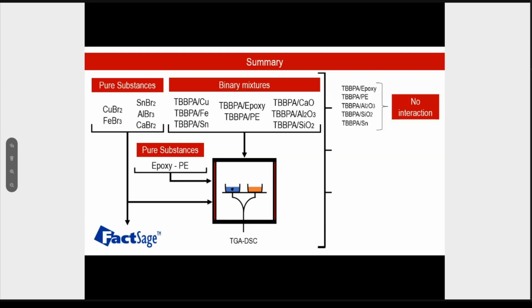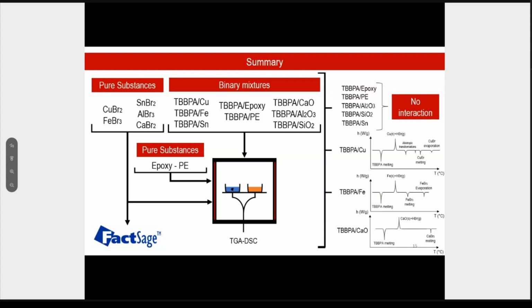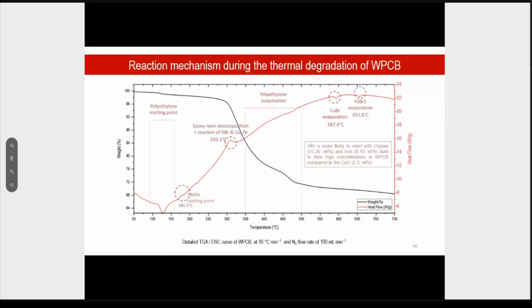From this study, we concluded that there is no interaction between the tetrabromobisphenol A and epoxies or any organic material, such as polyethylene, and also none between silica, tin, and metals like that with the tetrabromobisphenol A. However, there is a certain interaction between tetrabromobisphenol A and copper, iron, and also calcium oxide. They all share the same behavior, an exothermic reaction that takes place when hydrogen bromide is released to the atmosphere.